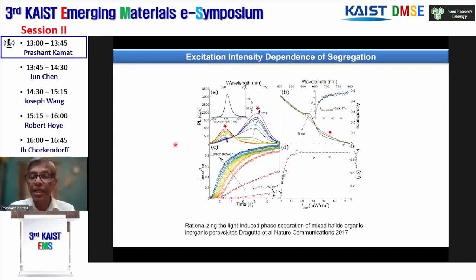So this is a mixed halide film, and you take it and you shine the light. And the first thing you see is the peak of this mixed halide peak goes down and the iodide peak goes up. In the same way, the emission of the mixed halide goes down and the iodide emission comes. Note that there was no bromide emission peak. So we can again do the intensity dependence study and other things.